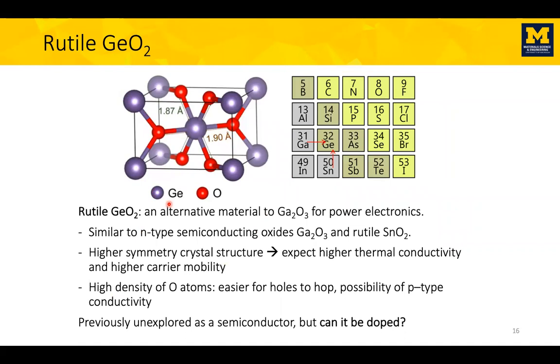So why is germanium oxide an alternative to gallium oxide? First of all, gallium and germanium are next to each other in the periodic table, so we expect that it should be similarly good to n-type dope. Another name of rutile germanium oxide is tin dioxide-like, and tin dioxide is a great semiconductor as well, a transparent conducting semiconductor that can be doped. So through the similarities, we're arguing that germanium oxide should be a good candidate.